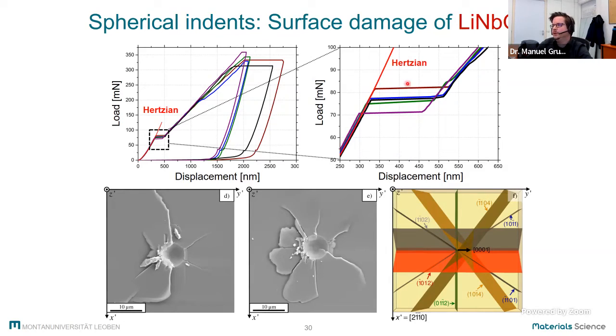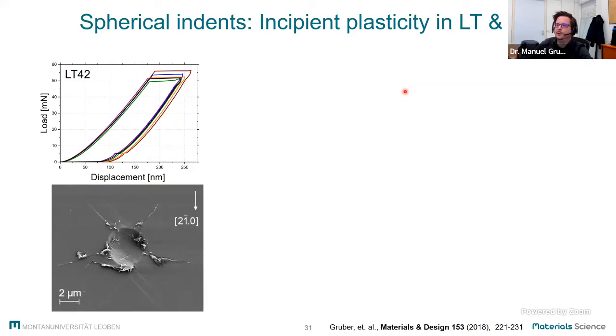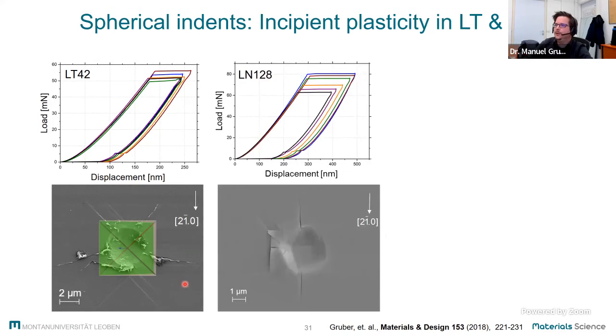So we interrupted our experiments at this displacement and wanted to see how our surface looks after spherical indents for very low loads and after the very first incipient plasticity in lithium tantalate and lithium niobate. And what we can see here is that we do not only have our cracks as seen before, but also plastic deformation in the same directions, in the same set of planes, for lithium tantalate as well as for lithium niobate. Here again, we have these traces of plastic deformation together with cracks in the same directions.